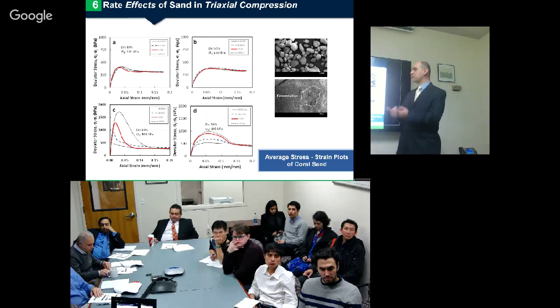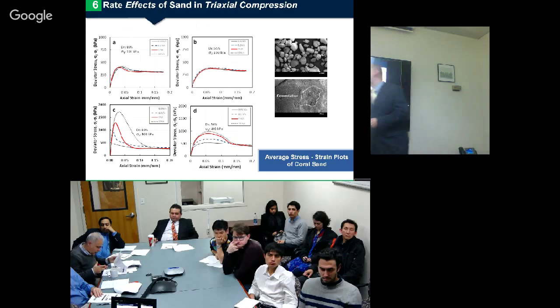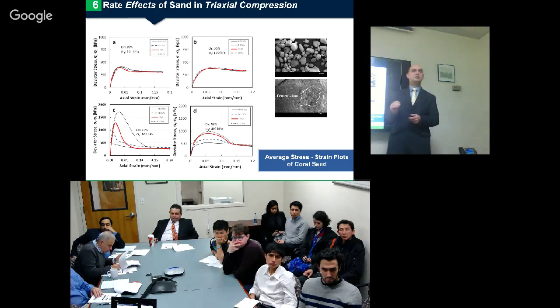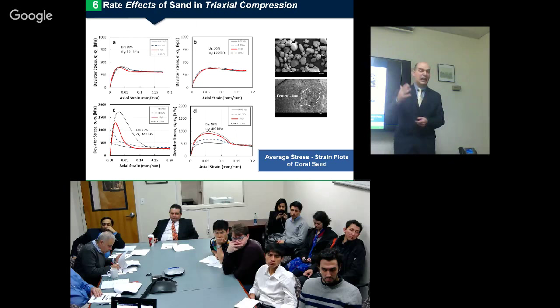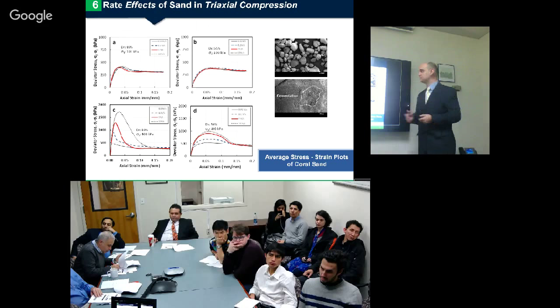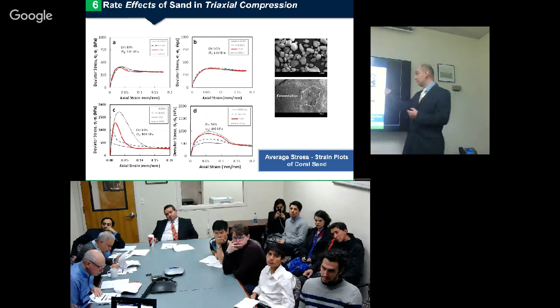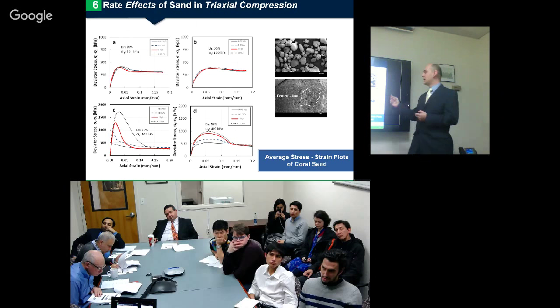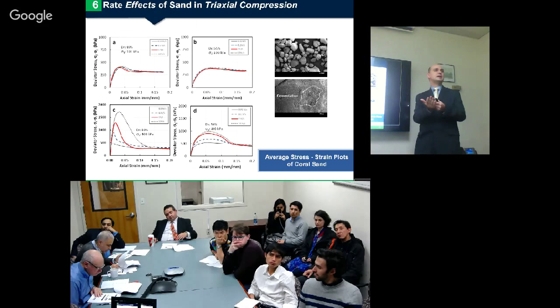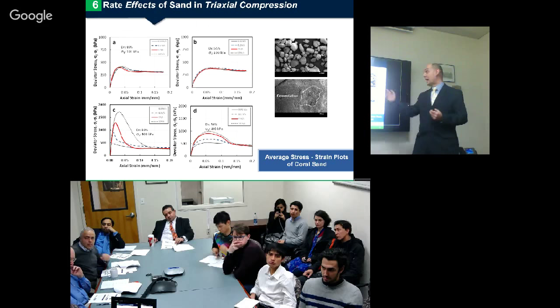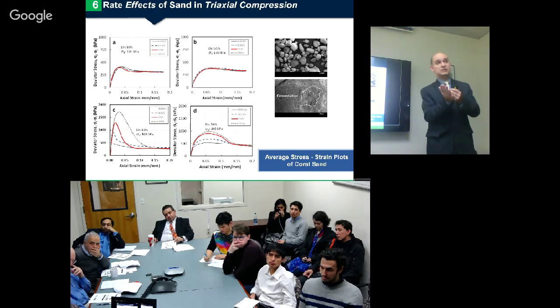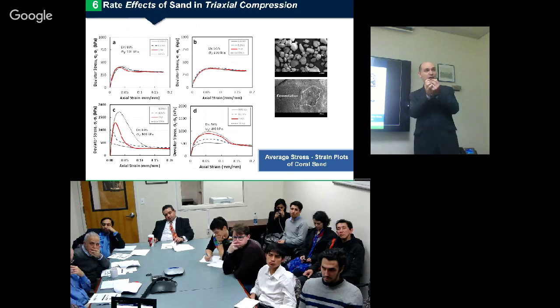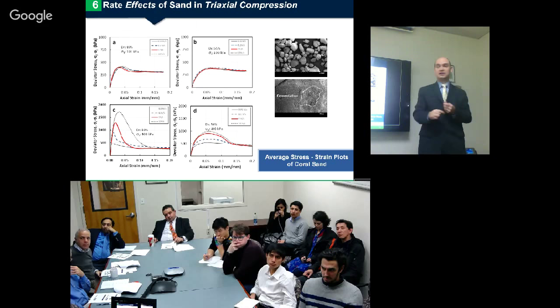Now, it brought my attention to see this huge peak of the deviator stress, and then after a sudden and significant drop after the peak, at the end they all go and follow the same ultimate stress. Looking at literature and previous studies, I found that the cementation component on the material, believe it or not, calcium-based material, might provide cementation effects. I noticed that also when the test is finished, the particles of the material are bonded together. That doesn't happen when you have silica material.